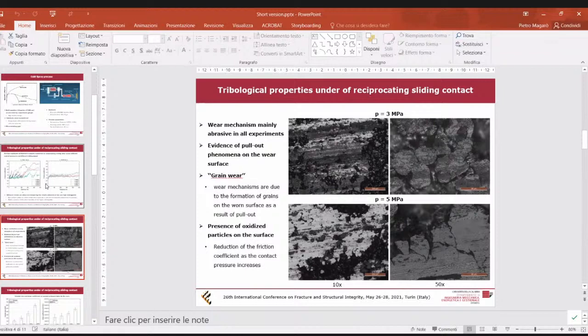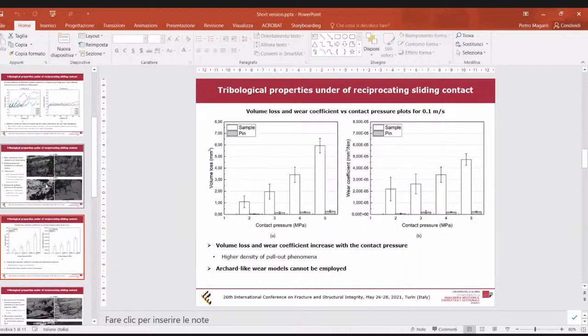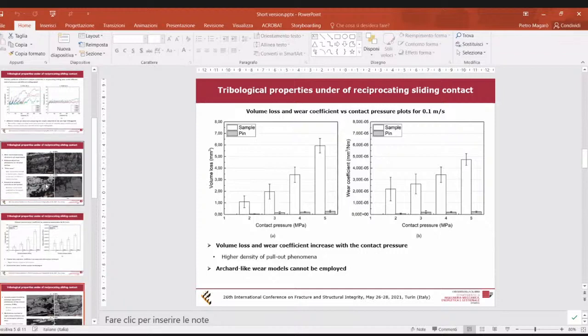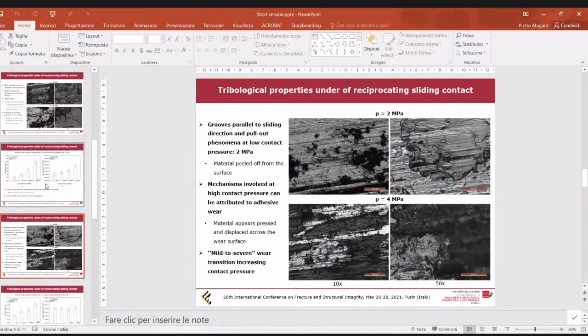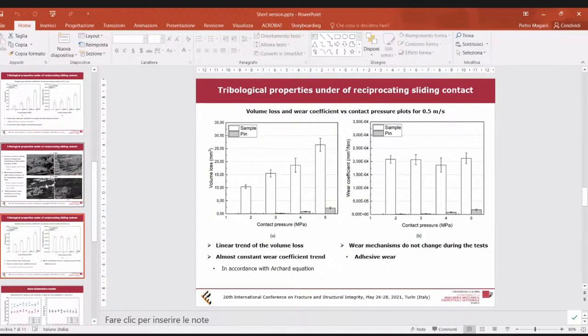At low speed, the wear mechanisms seem to be mainly abrasive, in particular due to pull-out phenomena that can be observed in this slide. These phenomena result in an almost linear trend of the wear coefficient. On the other hand, in this slide we can see that the damage mechanisms, in particular when increasing the contact pressure, seem to be mainly adhesive. In this case, the results show an almost constant trend of the wear coefficient. This result is also in accordance with the model proposed by Archard in this work.